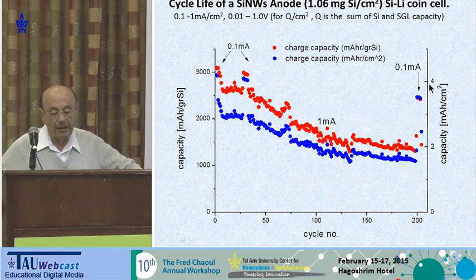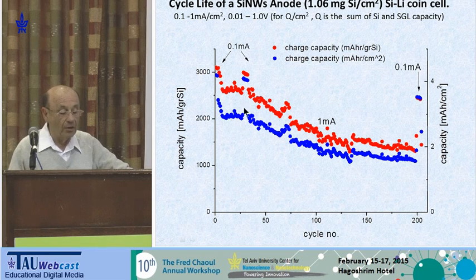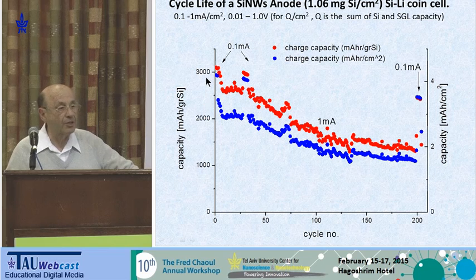But we had in mind that we need to fulfill the target of lithium batteries. Normally, what you have in your pockets or in your laptop is 4 milliamp hour per centimeter square. And this is the value that we were looking for. On the left side, you see that we got 3,000 milliampere hour per gram of silicon, which is about 70% of the theoretical value. Now, the question: why would the capacity drop with cycle number?